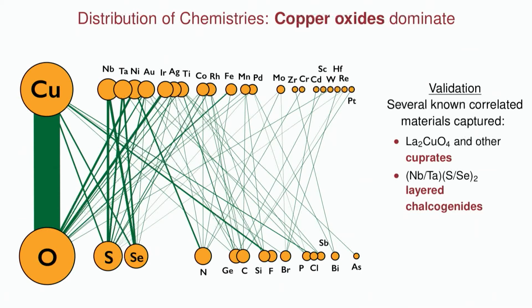A nice kind of validation here is that several known classes of strongly correlated materials are captured, are reproduced by this query. Okay, so one is these cuprates, such as La2CuO4. This is one of the classic parent compounds of the cuprates. We find that one. That would be a problem if we didn't, since we're looking for things similar to the cuprates. In addition, we also find other classes of correlated materials, such as these layered chalcogenides. And these systems are known to exhibit in some cases superconductivity and charge density waves and other interesting correlation phenomena. So a nice sanity check that our query is working here.